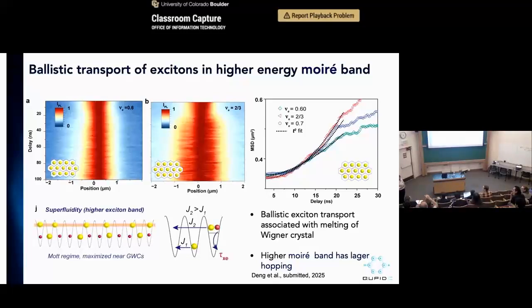So it's the excitons that are forming the Wigner crystal, not electrons? No, the electrons are forming the Wigner crystal, and the excitons are in Mott states, yeah. You said it's a micro-eV energy scale for the hopping of excitons. That's amazing, you can have that kind of order at 4K. The micro-eV scale is this lowest exciton band. We are thinking that when you put the exciton on top of the Wigner crystal, this J is going to become larger. The Wigner crystal of excitons, how is it different from a Mott state? There's no Wigner crystal of excitons here. It's just a Wigner crystal of charge.